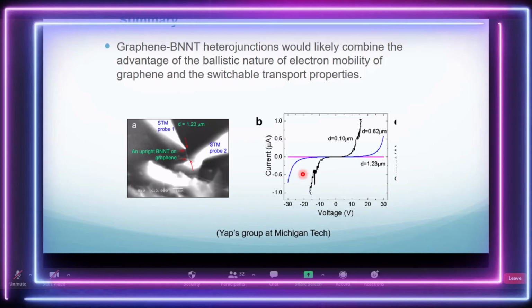But if you increase the thickness of the material, then we recover the properties of the material, which is then reflected in the IV characteristics. And finally, we also saw how you can modify the graphene by placing the BNNT on top of it. So we can retain the mobility, which is a strength of graphene, but at the junction with the BNNT, we again induce the diode-like behavior. So this is the end of this part.